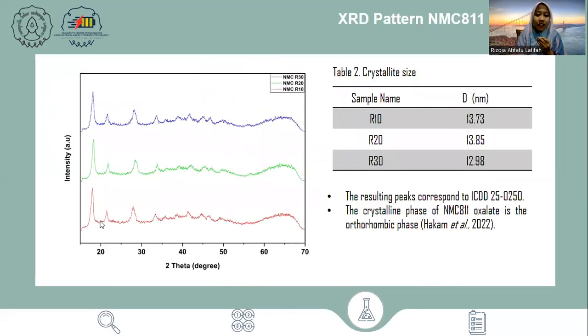The next is the diffraction pattern of nickel manganese cobalt material. The peaks correspond to ICDD number 25-0250, and the sharpest peak is obtained at 2 theta 17 to 19 degrees. The crystallite size obtained is presented in Table 2. The crystalline phase of nickel manganese cobalt oxalate is the orthorhombic phase.